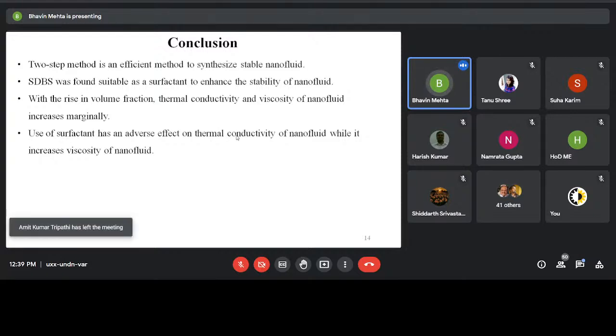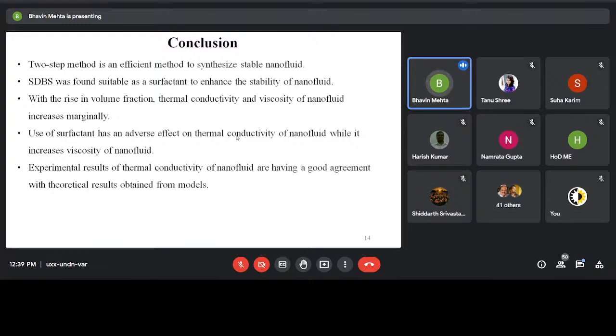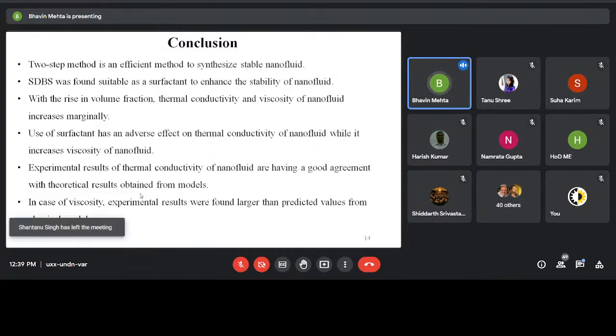So nanofluid without surfactant shows better thermal conductivity compared to nanofluid with surfactant. And there is a rise in the viscosity if we synthesize the nanofluid with surfactant compared to without surfactant. The experimental results of thermal conductivity of nanofluids are in good agreement with the theoretical models, while in the viscosity we found some deviation from the predicted values at a higher volume fraction.